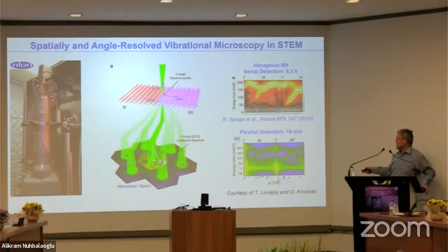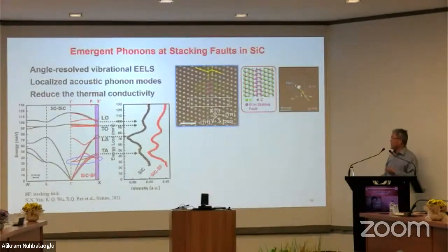But now with the new detector, it uses a much shorter time. With a direct electron detector with a small aperture, they can get this in a few minutes, quite a big improvement on the demonstrated technique that we have further developed. So by using this vibrational EELS method, we can study the phonon characteristics at an individual defect. This is just a single stacking fault in silicon carbide, 3C, cubic silicon carbide. You see, this is one crystal, another crystal, you have one shift. This is the stacking fault. By using a large converging angle, we get a spatial resolution. And then we study the phonon EELS spectrum from the interface, from the defect, and from the bulk. You can see they are different.